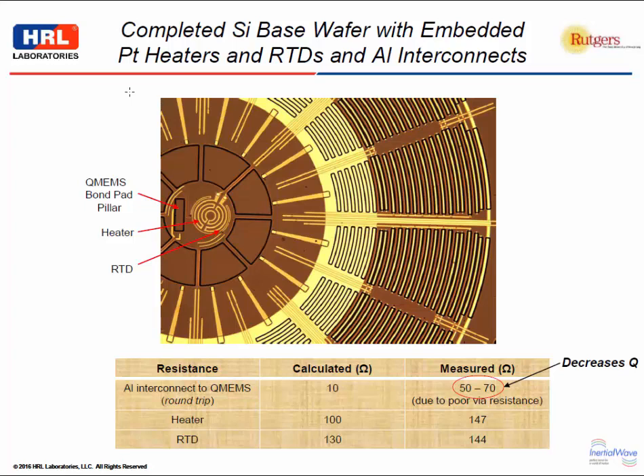This is an actual picture of the completed silicon base wafer with the embedded platinum heaters and RTDs and the aluminum interconnects going out. This shows the heater again and the RTD and the bond sites for the quartz. We tested the RTD and heater resistances, and we were calculating about 130 ohms. We were getting about 140, 147 ohms. The big issue that we had was we calculated the interconnect resistance for the quartz device of about 10 ohms through these aluminum interconnects. And as I mentioned, through the vias, we did a poor job at keeping that via resistance down, and we were getting more like 50 or 70 ohms round trip. So that decreased the Q, and I took that into account when we made the final measurements.